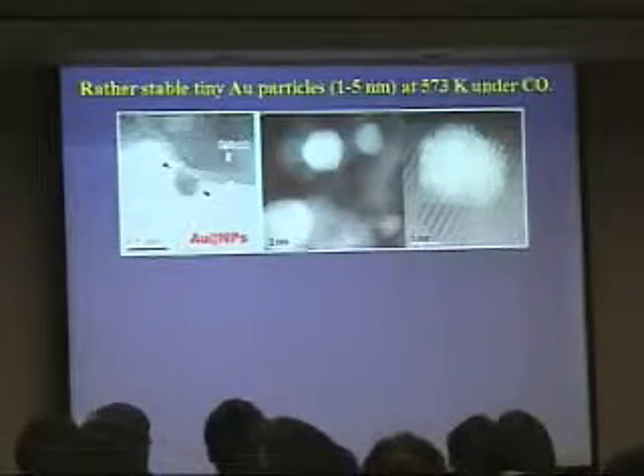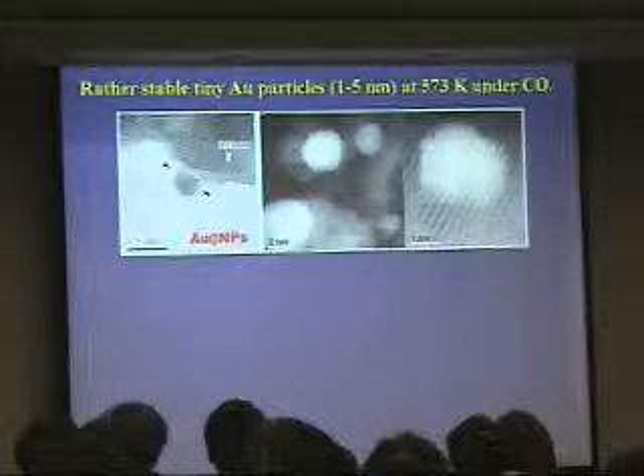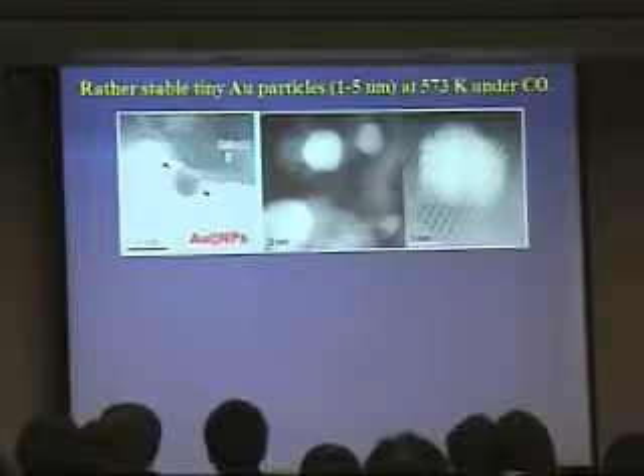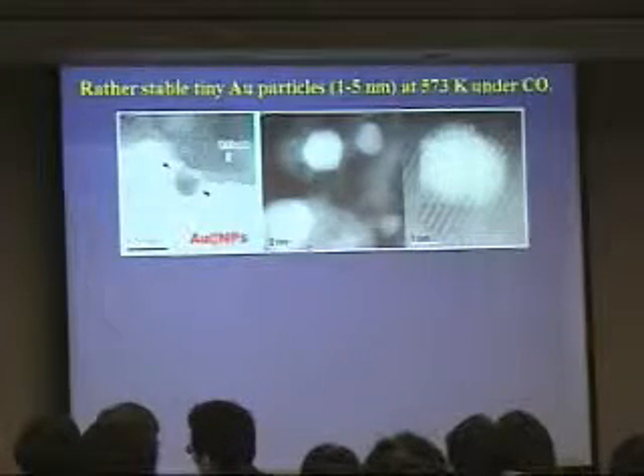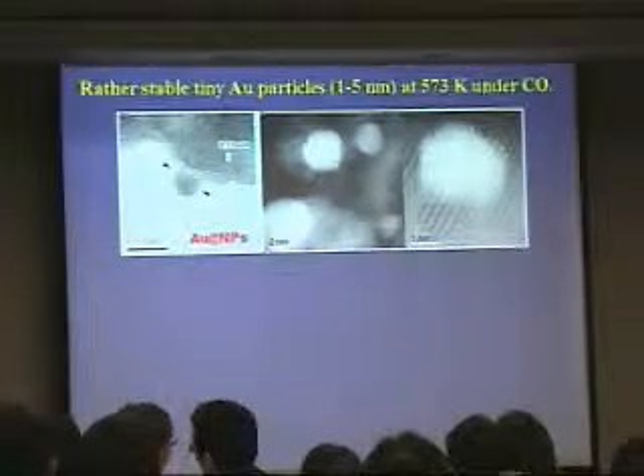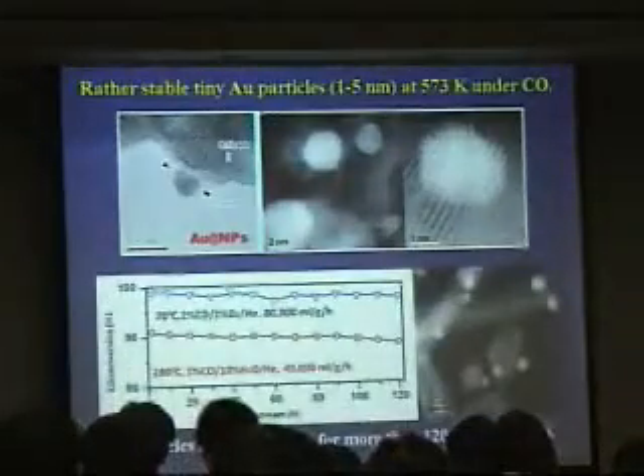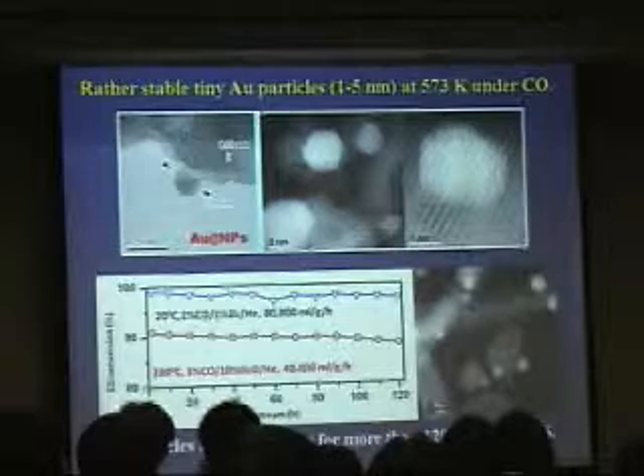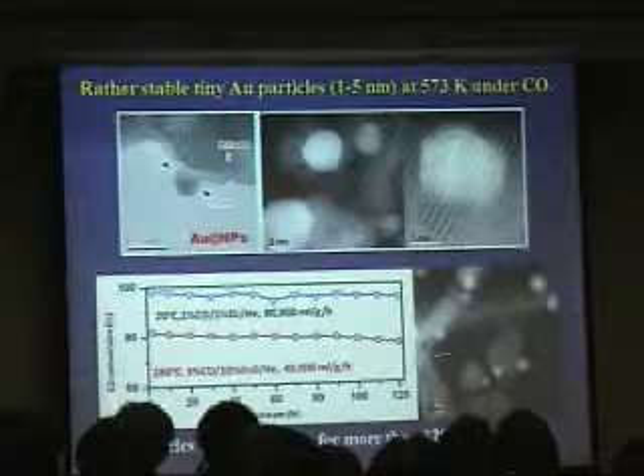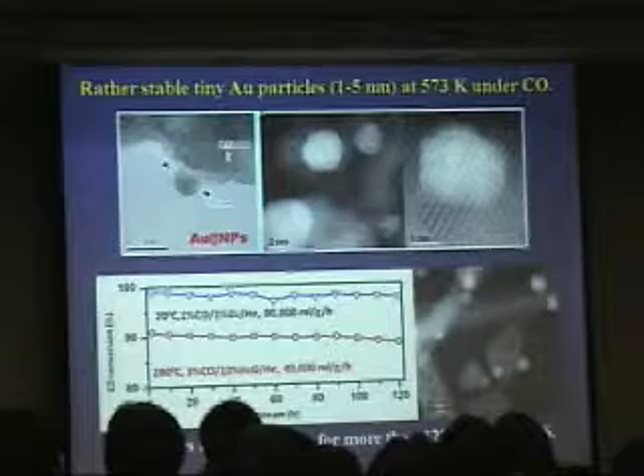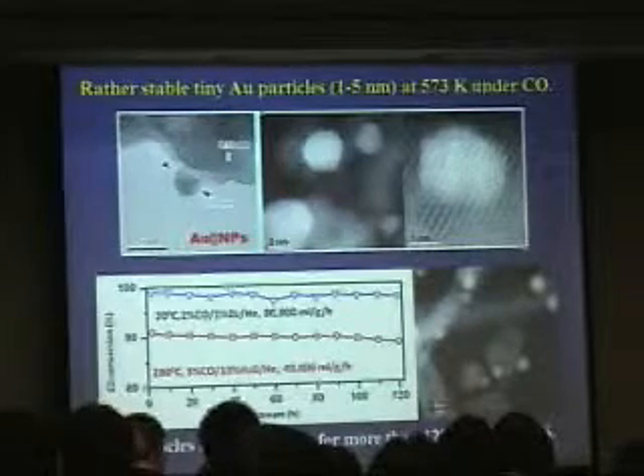And so this is for TEM. The best TEM can also heat the temperature to 600 degrees C, but can only introduce a small amount of atmosphere, like 10 torr or something like that, because of the resolution problems. And then we want to confirm it with the really strongly bonded gold particles. We use it for the water gas shift reaction at this high temperature and for more than 100 hours.